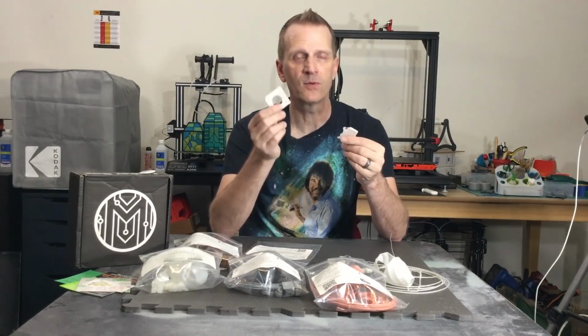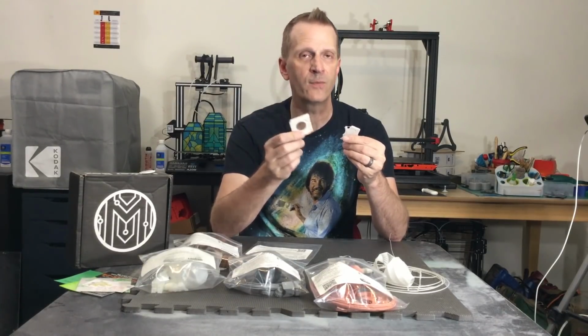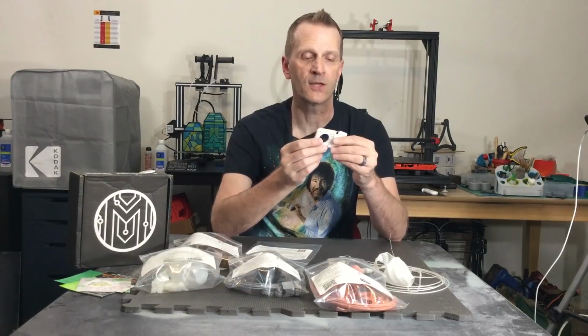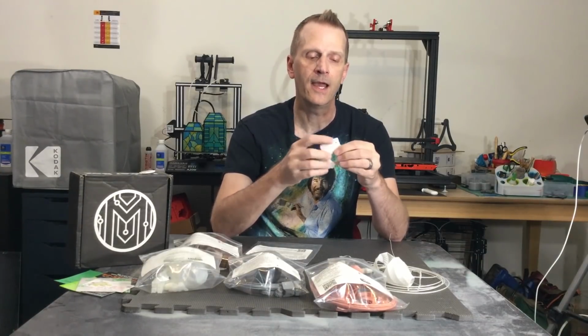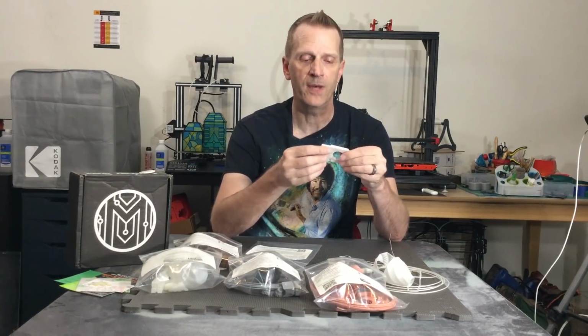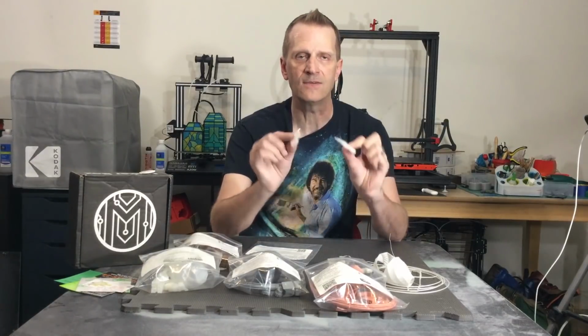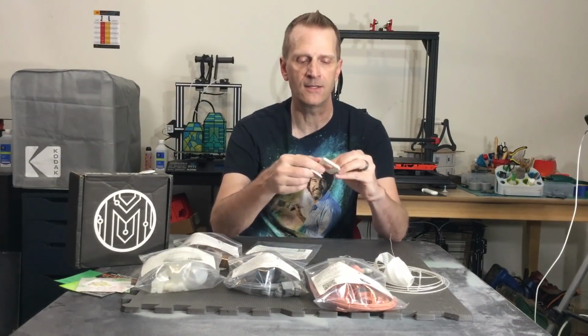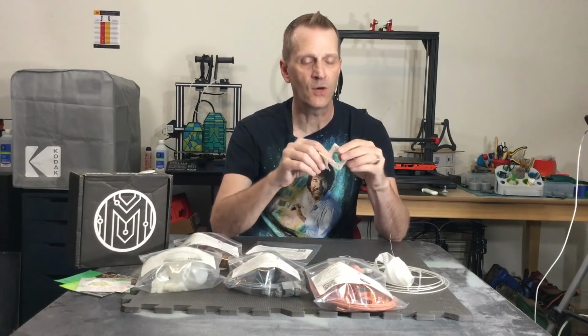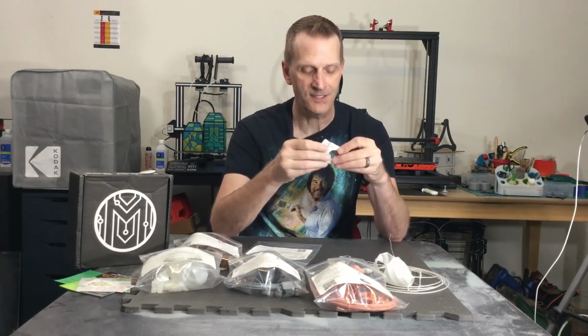It looked really great. We did 2 perimeters, 2 top layers, 2 bottom layers, 25% infill at 40 millimeters per second with a half speed on the first layer. And the print turned out great. I took it off the print bed, and then I was able to easily break it in half. And I can see that there's no layer adhesion. So I don't think dropping the temperature down was a good idea.